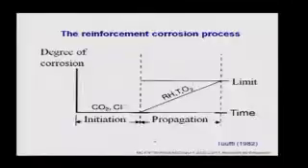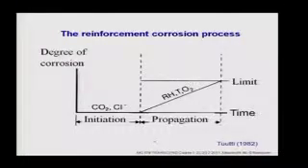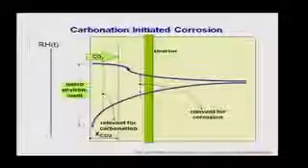This is the kind of service life model we have — you also saw that picture yesterday. This is a service life model invented a long time ago, mainly on reinforcement corrosion but also applicable for most other deterioration processes. You have an initiation period where no damage occurs, then a propagation period where you can measure and see the damage. Usually when doing service life design, we limit the service life to the point where the initiation period has come to an end — for reinforcement corrosion, that is simply two transport processes: carbonation and chloride ingress to the steel.